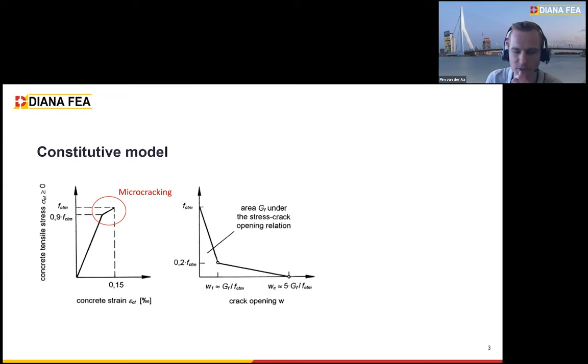The first thing is the constitutive model, which is actually in the model code. This is just for plain concrete. What you see here is that the left side describes the stress strain relation up till cracking, and the right side describes the stress crack opening relationship. What is important to highlight here, and what I would like to get into, is the pre-peak branch, so the branch between 0.9 fctm and the tensile strength. Why is this introduced? The reason was to also capture the micro cracking.